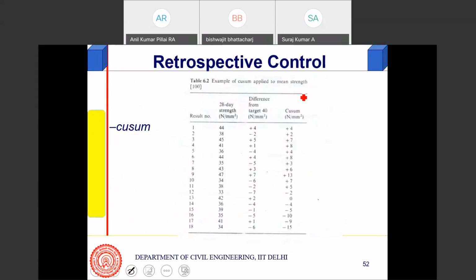So there's something called the cusum method, the cumulative sum method. And many codes have this actually. BS EN do have this kind of a quality control system, both for mean as well as standard deviation. So for example, if I have result numbers, and these are my strength values, this would be accelerated strength. Again, I'm saying, so they don't have to wait for 28 days. Now your target strength was 40.